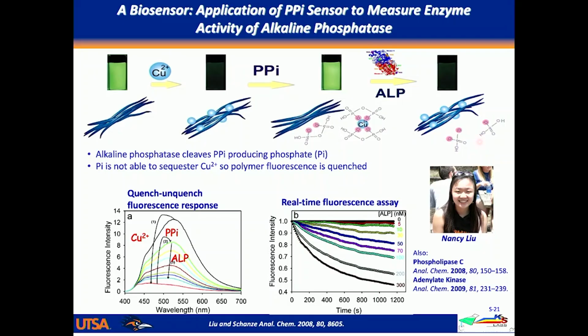We actually were able to calibrate these enzyme kinetics with known kinetics of the enzyme under the same conditions. And so now what we're using is this nice fluorescent conjugated polymer as a sensor for a bioreaction. Nancy, as part of her thesis, sort of generalized this to a family of different enzymes that basically take advantage of the same kind of catalytic effects, but using the polymer again as a transducer.